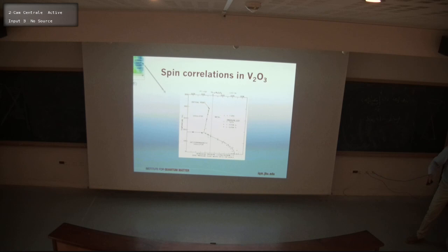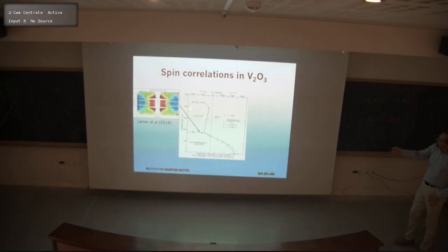So the point basically that I'm trying to make is that in this part of the phase diagram, in this material, we have a highly frustrated spin system. And perhaps that is part of why the Mott transition actually rears its head, in a sense, is that the system is not able to achieve magnetic order because of that frustration. And so, therefore, it's possible to have this exposed